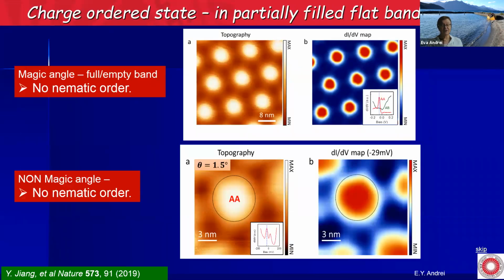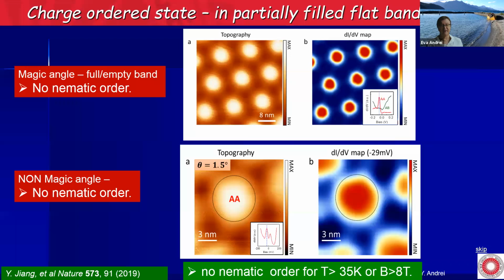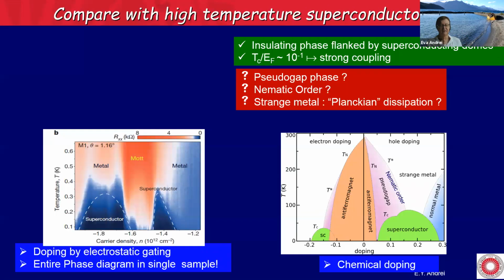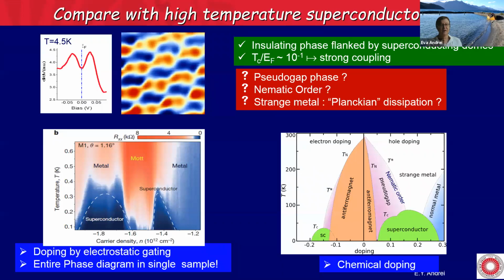Now just to make sure that this is not a simple strain effect, for example, if we do the same experiment in the full or empty band, we see none of this charge redistribution. If we do the same thing at an angle that's not a magic angle, for example 1.5 degrees, where we no longer have a flat band separated by gaps from dispersive bands, this whole physics goes away. Importantly, in the same sample, the charge nematic order disappears above 35 Kelvin or above 8 Tesla. So clearly this is a property of the correlated state that is created by bringing the Fermi energy into the flat band. So going back to our comparison with high TC superconductors, where are we standing here? So we have a pseudo gap phase, yes. We have nematic order, yes.